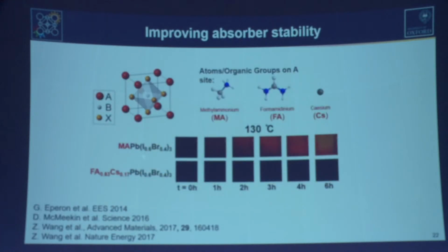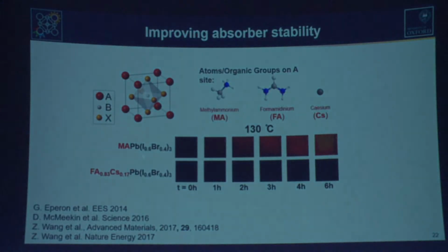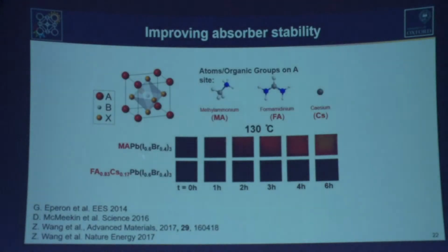As well as using these single ions, we can also mix them, which can improve stability. For instance, formamidinium is actually slightly too large for the crystal, cesium's a little too small, and methylammonium's a little too volatile, but if we mix formamidinium and cesium together at the right blend ratio, we can get something that works well, creates an ion that's the right size and is stable. This is an example of what we call a mixed cation, mixed halide lead perovskite.